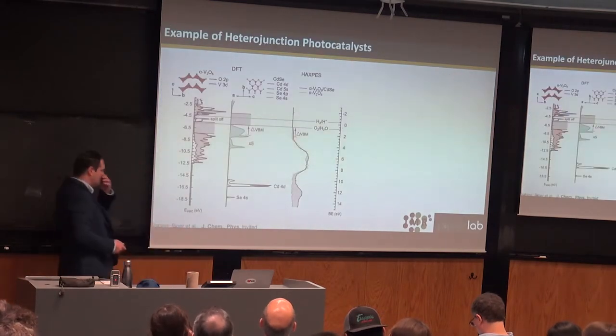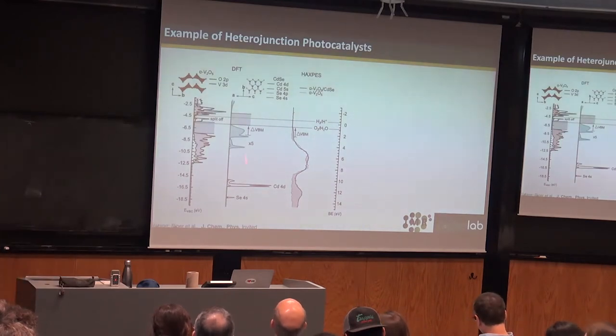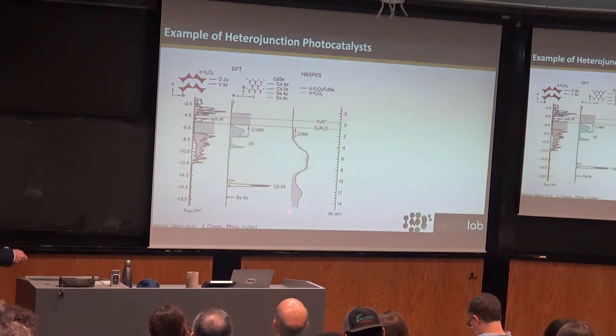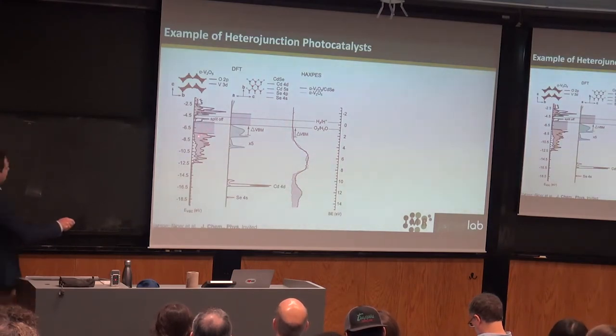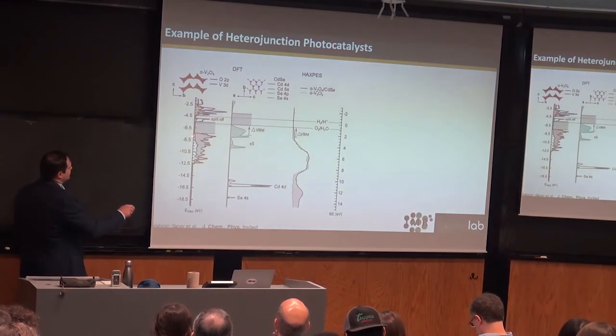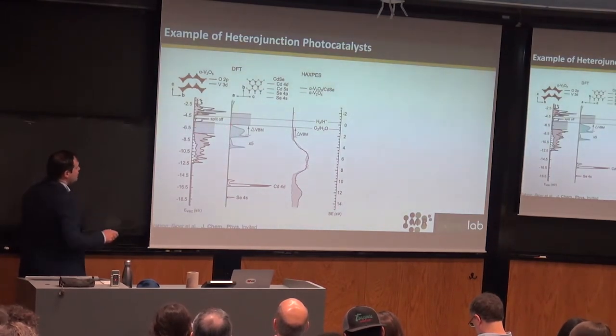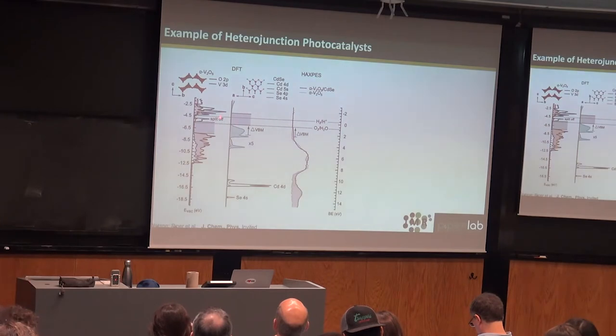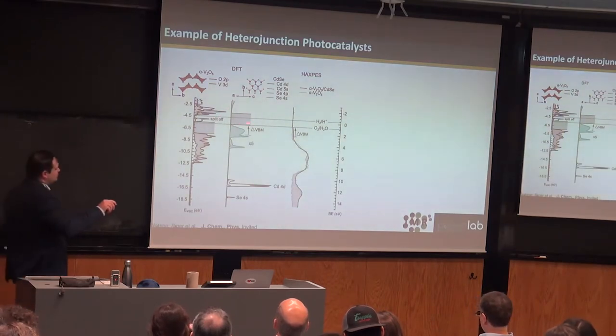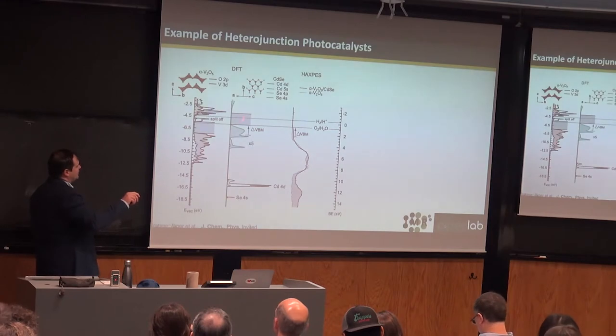So what can we do? The idea is we can combine our computation and measure it. We can use a DFT to look at our spectra and determine what sort of valence band offset we actually have. In the case of just the bare V2O5 versus the cadmium selenide, which will be our light harvesting quantum dot, we have an offset where the V2O5's valence band is much below this point here. With cadmium selenide, you don't really want this so much because holes build up on this side, because you're going to have light and your electrons will transfer this way.